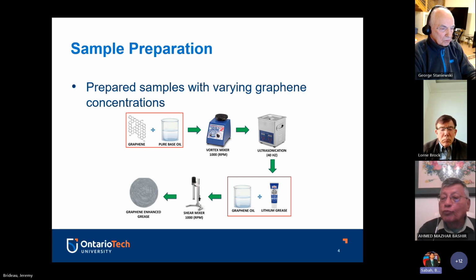So what we do is we get some pure base oil from Petro-Canada. I think it's grade 2 and 3. And then we put the graphene inside the base oil. The reason we do this is that graphene can't mix completely homogeneously inside lubrication grease by itself. It needs that pure base oil from Petro-Canada in order to mix fully.